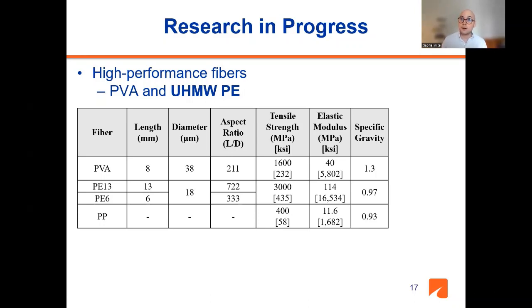Now, this ultra-high molecular weight polyethylene fiber, which is a new fiber that we're testing, you can see in the table, I have it as PE13 and PE6. The number denotes the length of the fiber. These have a much higher aspect ratio than the PVA, much higher tensile strength, much higher elastic modulus, and they're lighter than the PVA. So this is a very high performance fiber, which helps us reduce the fiber content of the system while still exhibiting the performance that we're looking at of this material.